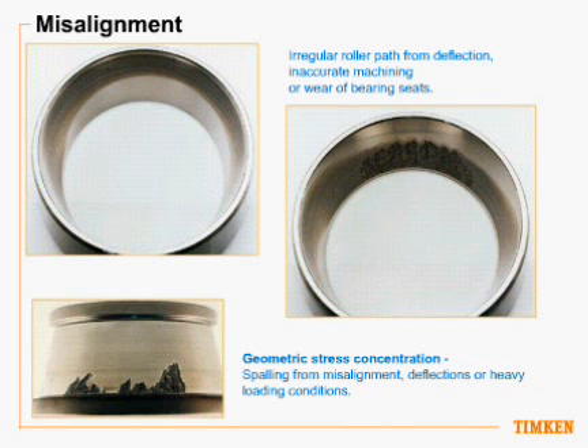Okay. The bottom photo there shows the effects of the misalignment on a cone, and you'll notice how all the spalling is occurring at the one edge of the raceway. What that's telling me is that the loading to the roller was concentrated on one side or the other. What are some examples, Rick, that can cause this to become misaligned during installation? Yeah, during installation, the number one cause I would say is the cup not being seated all the way in the hub, so it actually be cocked in the hub.